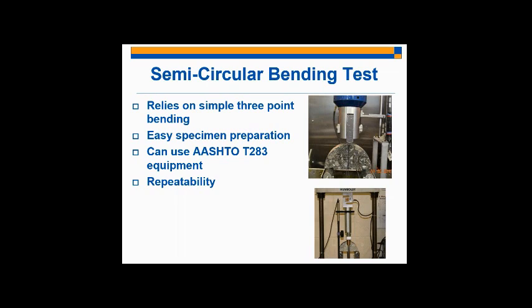And in terms of repeatability, we've seen very good repeatability values, typically below 15% coefficient of variance, actually typically below 10%. So we've really minimized the variability in this test. Our results are significantly more repeatable than when we started.